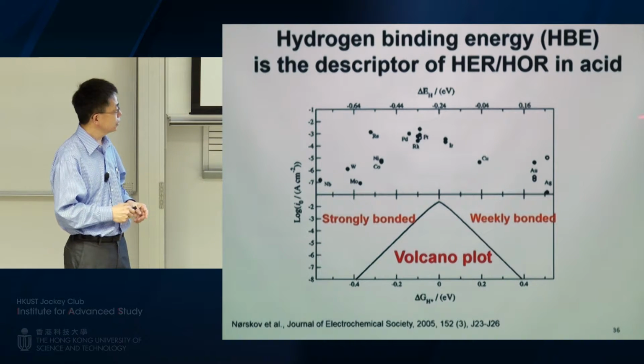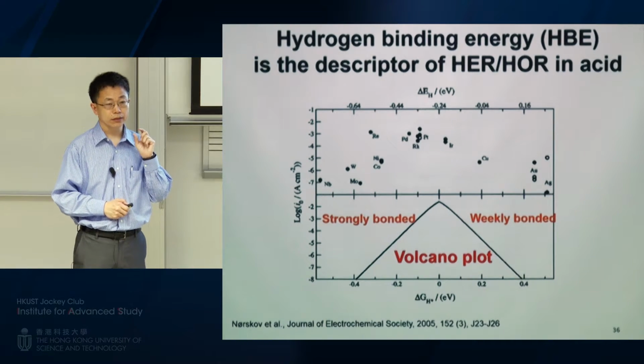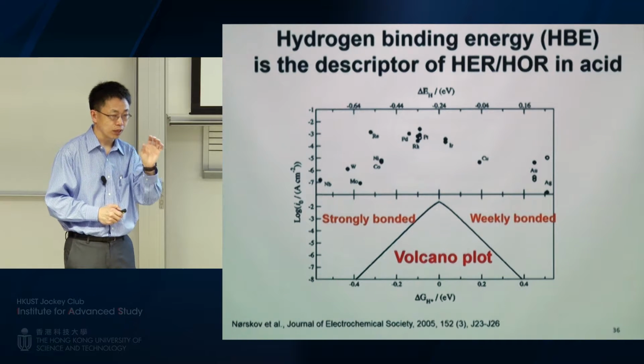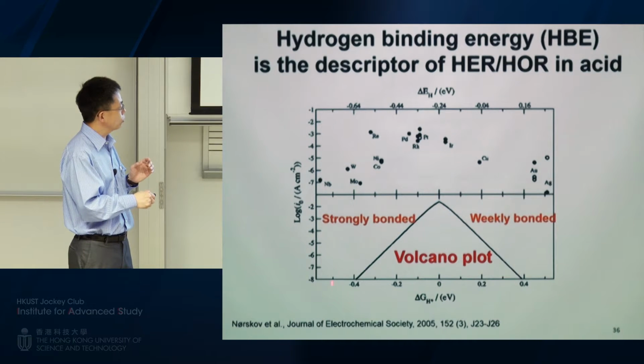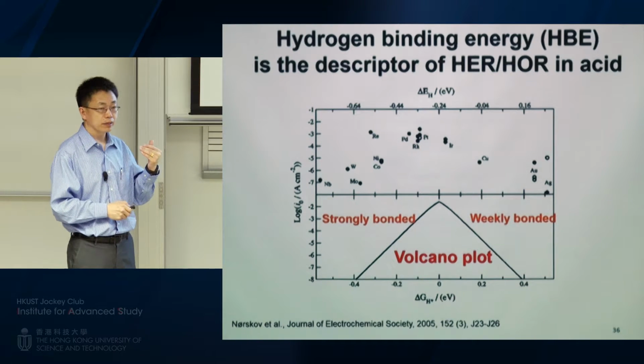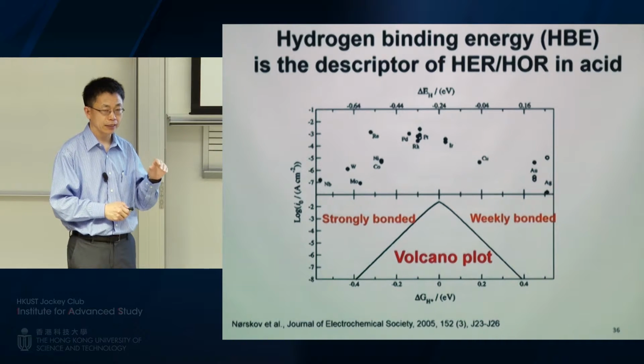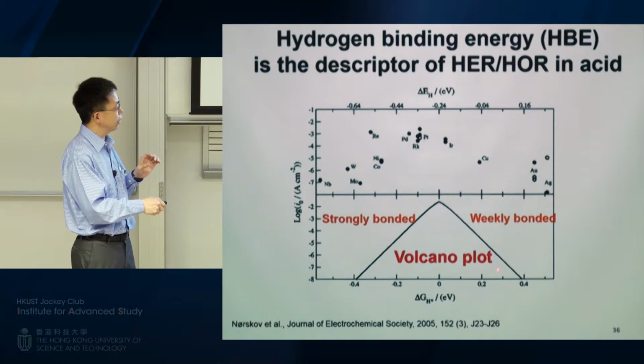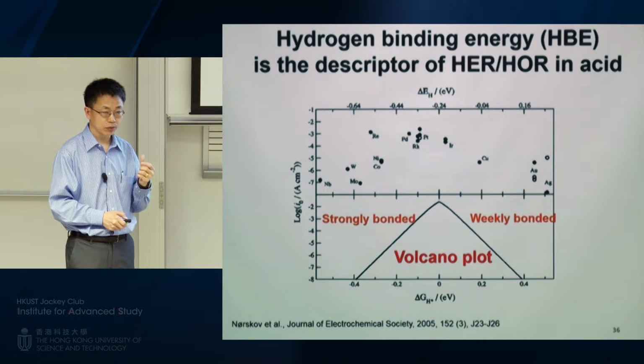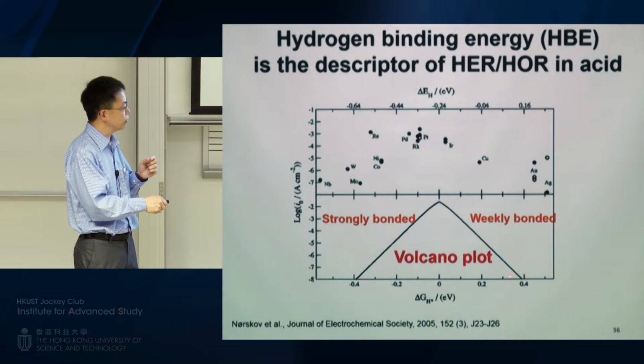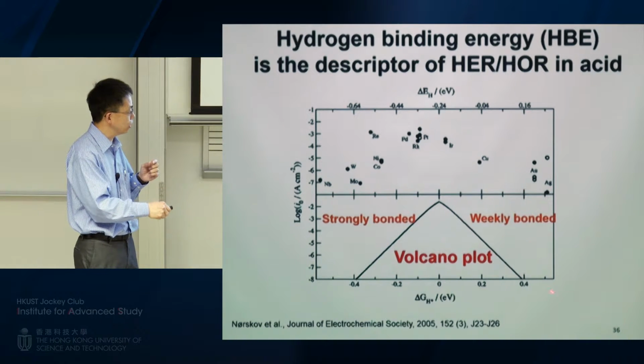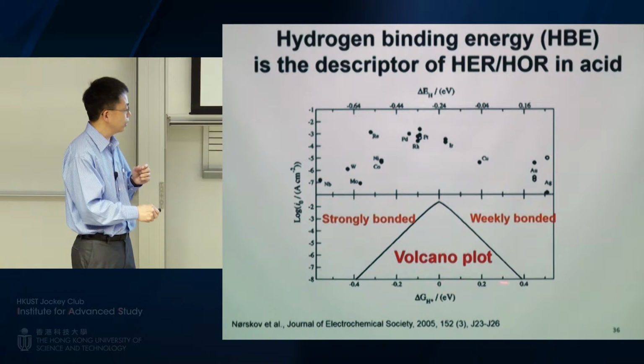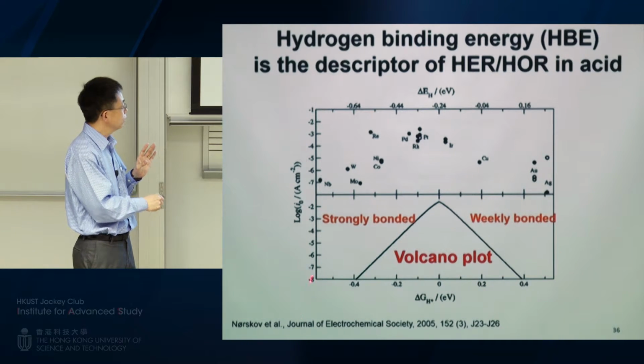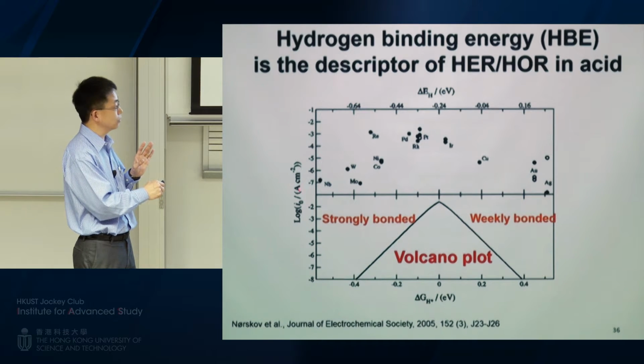So the expectation is you want to have the metal absorbing the hydrogen atom just of the right strength. If you do the adsorption too strongly, the intermediate will not want to leave the surface, making the reaction slower. Or you have the adsorption too lightly, and then the catalyst doesn't have the opportunity to influence the reaction, so you're going to have very low reaction rate. So the expectation is you're going to have this volcano plot. And the horizontal axis here is the hydrogen adsorption strength. The vertical axis is the exchange current density, or the activity of the HER reaction.